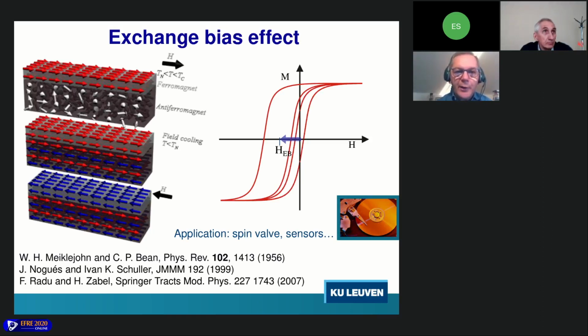When you look at the cartoons here at the left, you actually look at a bilayer where at the top there is a ferromagnetic cobalt layer, and at the bottom there is a cobalt oxide layer. When you're at room temperature, you're above the Néel temperature of the antiferromagnet, so the antiferromagnet is disordered, and there is of course ferromagnetic order. Then you will measure just a normal hysteresis loop.